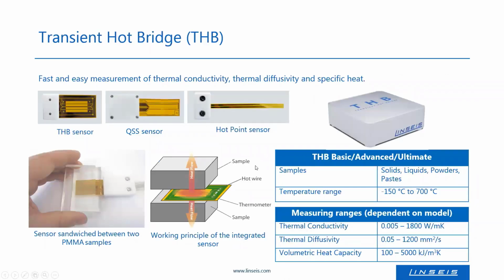With the THB, one has, as mentioned, a rather simple setup. So there are some foil sensors which need to be clamped in between two sample pieces. The sensor heats then the sample and measures at the same time the temperature increase of the sample. And from this information, one can then obtain the thermal conductivity. The LFA and the THB can be also used to determine the thermal conductivity of a polymer, for example, in a liquid state.